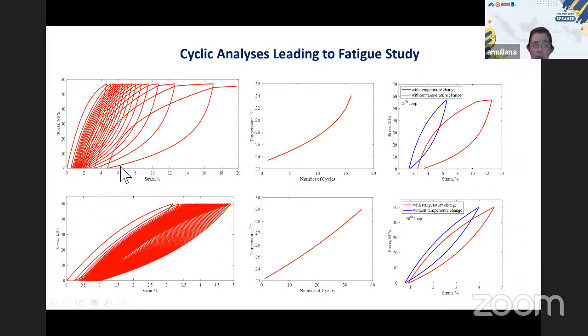Now, because of the dissipation mechanism, when we accumulate more and more cycles, the energy being dissipated is converted to heat. That would increase the temperature of the body. As the temperature of the body increases, it will affect the performance of the polymer. So when we see all of this in the long run, we would like to study or predict the fatigue failure of this material. But now we don't have the experimental data yet. So up to this point, it is only simulation that we observe.